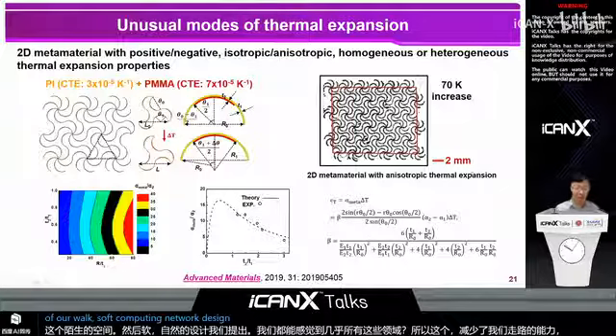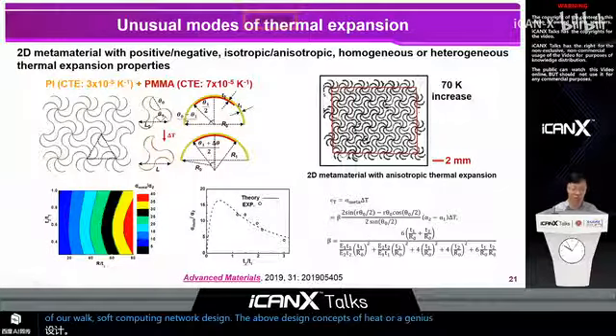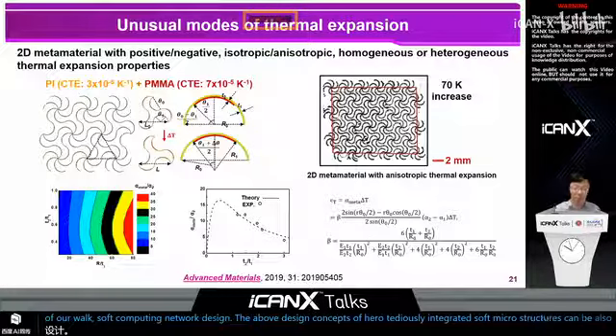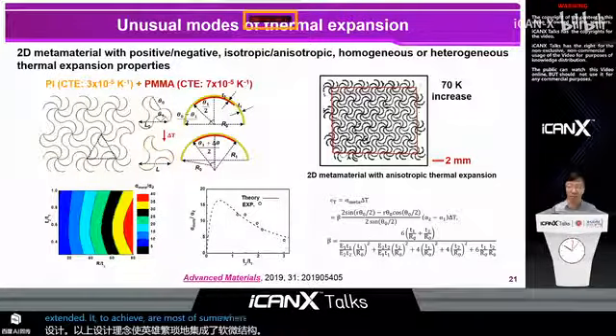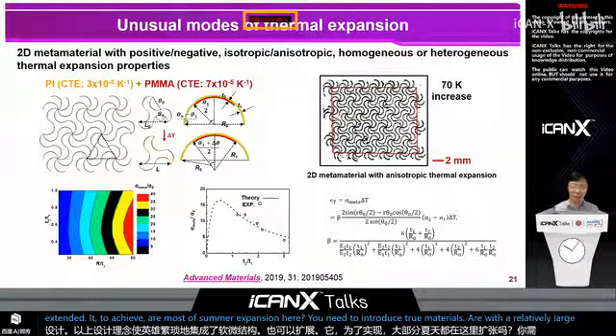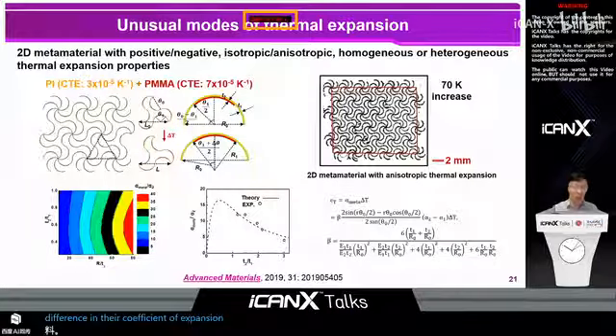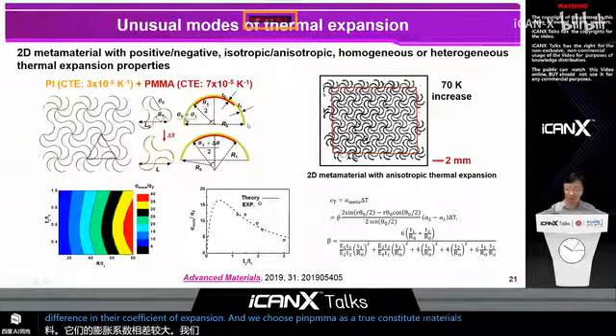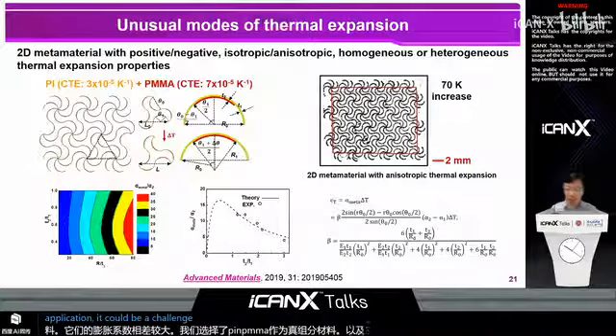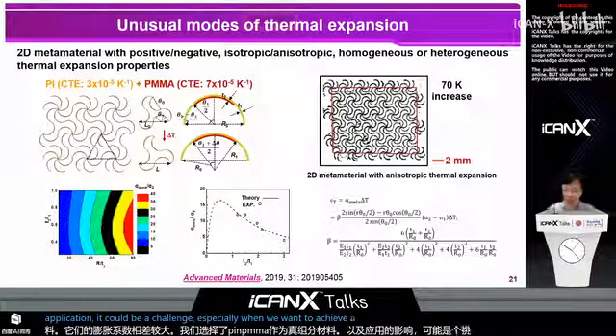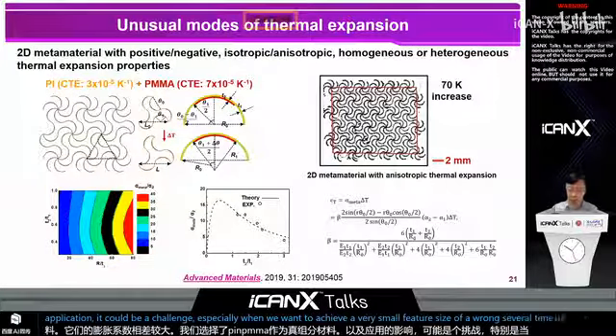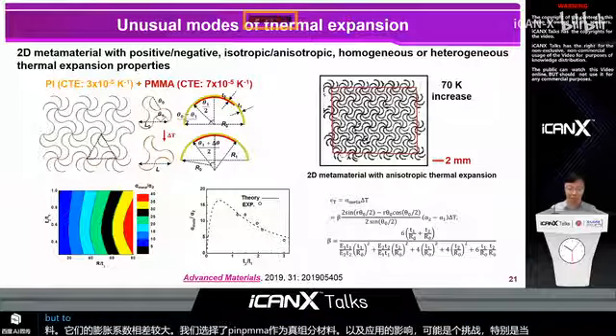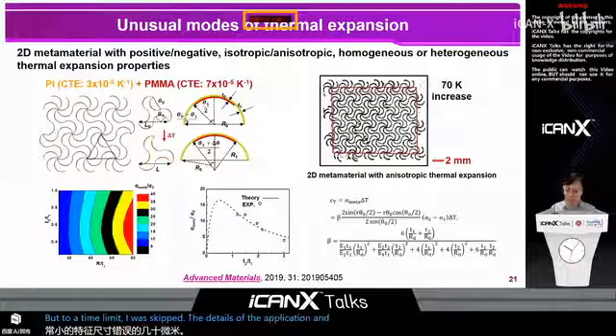The above design concept of heterogeneously integrated soft microstructures can also be extended to achieve unusual modes of thermal expansion. Here you need to introduce two materials with a relatively large difference in the coefficient of thermal expansion. And we choose PI and PMMA as the two constituent materials. In terms of the fabrication, it could be a challenge, especially when you want to achieve a very small feature size of around several tens of microns. But due to the time limit, I will skip the details of the fabrication and just show you some results.